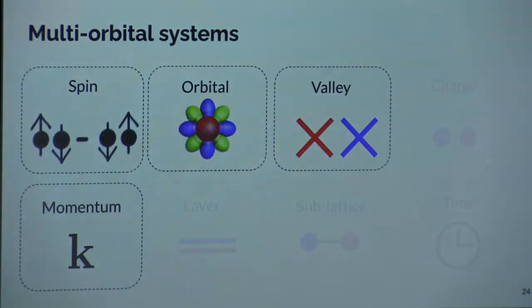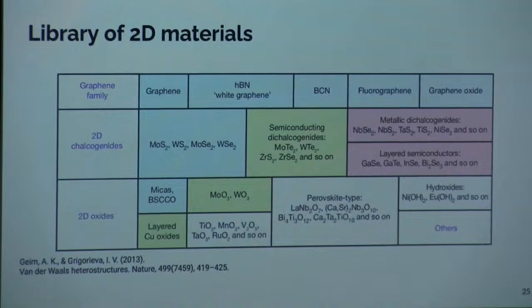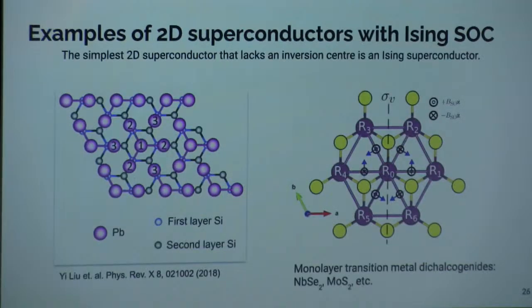So here, beyond spin and momentum degrees of freedom, we also have an orbital degree of freedom. Monolayer TMDs are part of the family of 2D materials. They are usually regarded as the more complicated siblings of graphene. You can find them in their metallic forms and also in semiconducting forms. The semiconductors, you can either dope or gate them, such that they also become superconducting. Monolayer TMDs are also Ising superconductors. Ising superconductors are the simplest family of non-centrosymmetric superconductors there are.